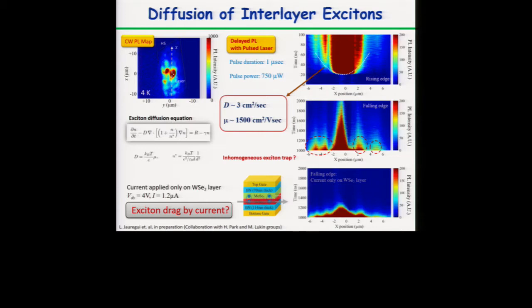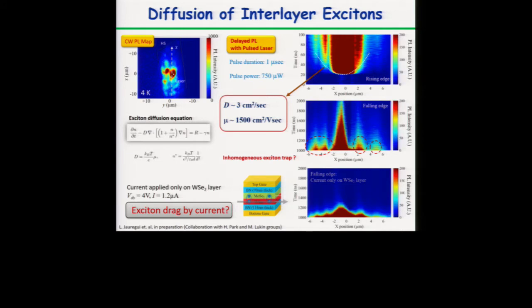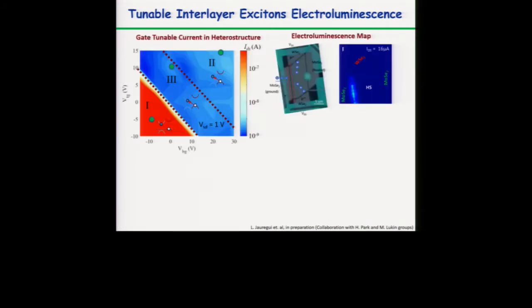On the plane of tungsten diselenide, it might be that the voltage we're applying on tungsten diselenide is helping to get rid of these exciton traps, or these inhomogeneities. What's the density approximately for the interlayer excitons when you put the laser on? Okay, let me go through it in a couple of slides, but I can tell you right now that from our calculation it's around 3×10^11 per square centimeter.